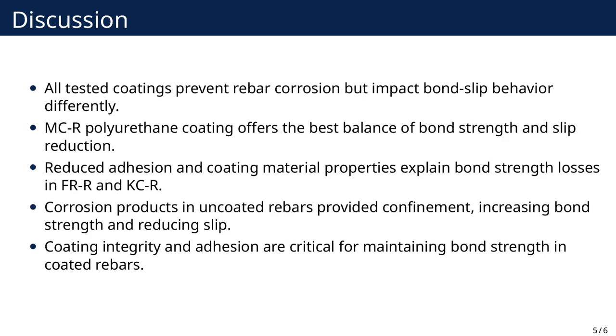The study demonstrates that while all tested coatings effectively prevent rebar corrosion, they have varying impacts on the bond slip behavior with concrete. The MCR polyurethane coating performed best by showing the least reduction in bond strength and reducing rebar slip. The significant reduction in bond strength for FRR and KCR coatings is attributed to factors like reduced adhesion and the nature of the coating material.